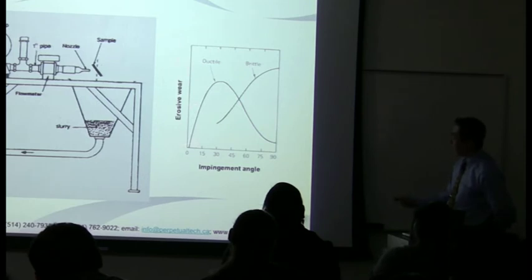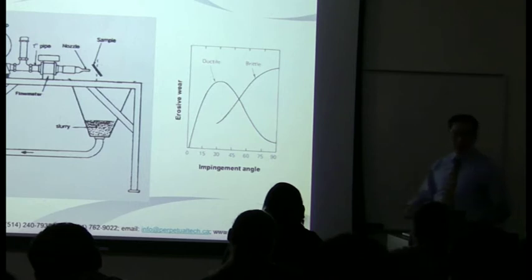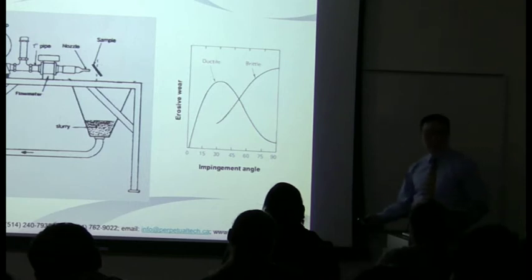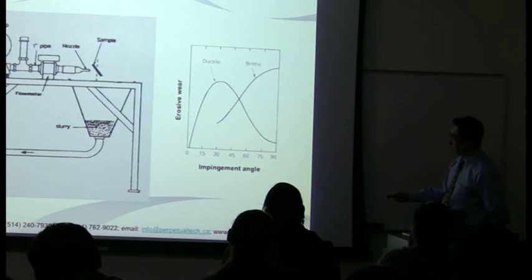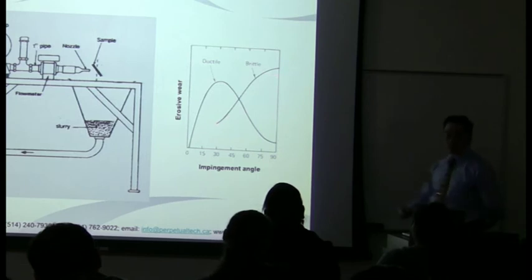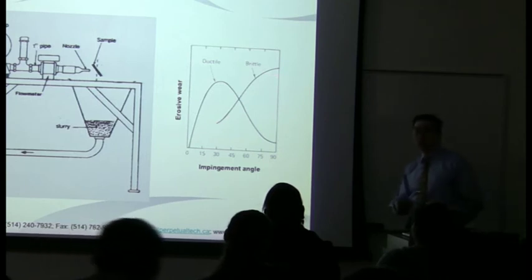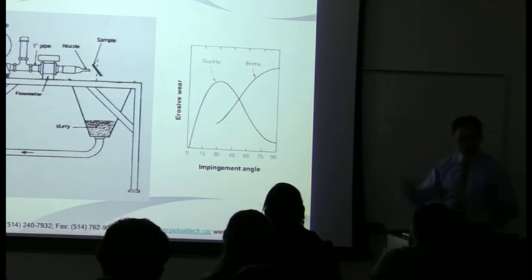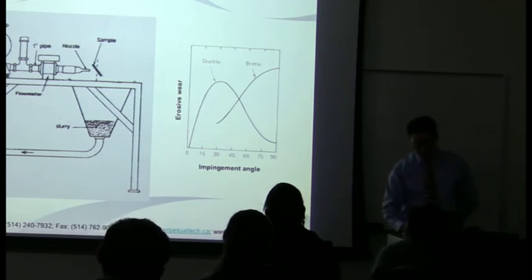You have erosive wear versus impingement angle. And you can see, depending on the type of material, you get very different types of wear. For ductile materials, they wear a lot at relatively low angles, around 30 degrees. And then it decreases dramatically at high angle. Whereas it's the opposite for brittle materials. So it's important, if you want to really know and understand how your material is going to perform against erosion, that you do it at different impingement angles.